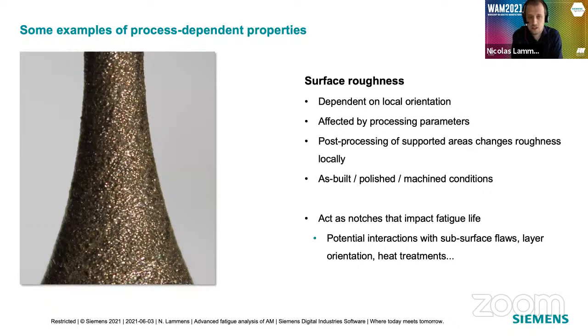And to give you some examples of these process-dependent properties that we consider now in our research, and to be clear, this is ongoing research. So we don't have the final answer yet. I think everyone in this workshop and in the world is working towards getting solutions for this, but we are not there yet. But one of the properties we consider is surface roughness. Now, surface roughness has existed in any kind of manufacturing, but when you go to the level of additive manufacturing, there are some extra complexities, because surface roughness is no longer a property of the component. It becomes a local property, because depending on the orientation of your component, you get different surface roughness. For example, in the picture here, the part that is almost perpendicular to the build direction has different surface roughness than the part here at the bottom.